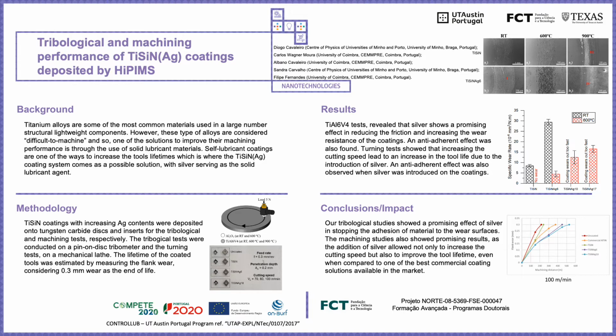As a little background, this work focuses on the difficult to machine titanium alloy, titanium aluminum 6 vanadium 4, and the use of solid lubrication to replace liquid lubrication in an effort to improve the machinability of this type of alloys. In this work, we use the well-known titanium silicon nitride system for its good mechanical and thermal properties, and as a solid lubricant agent, we use the silver.